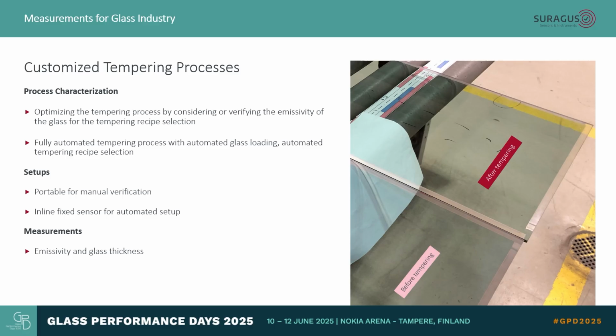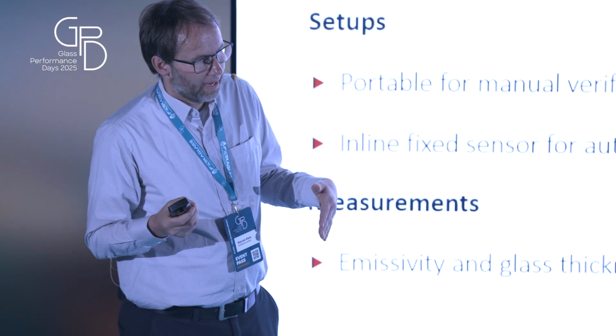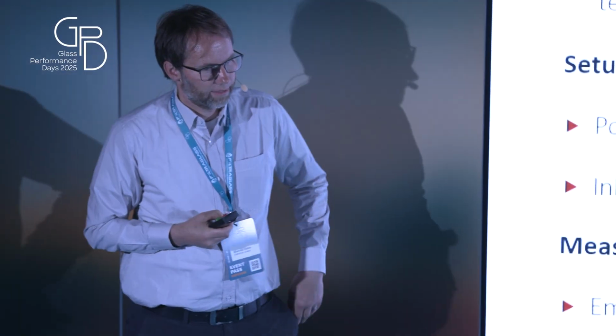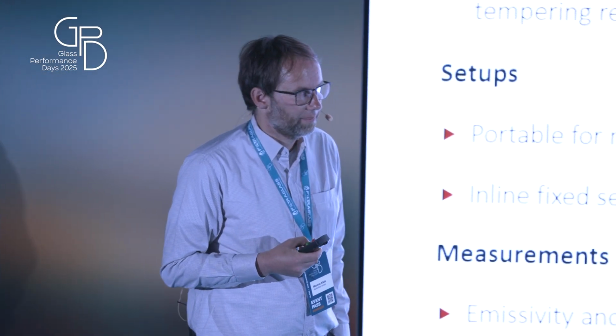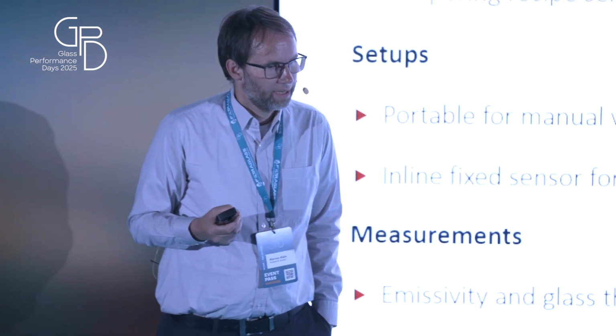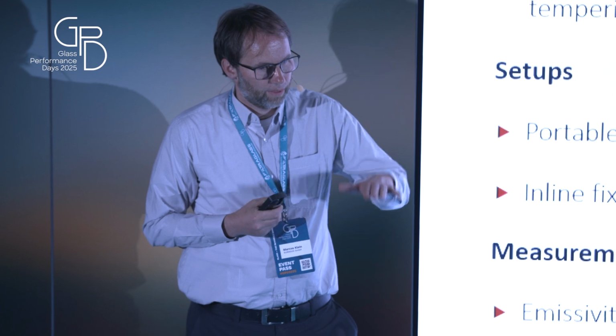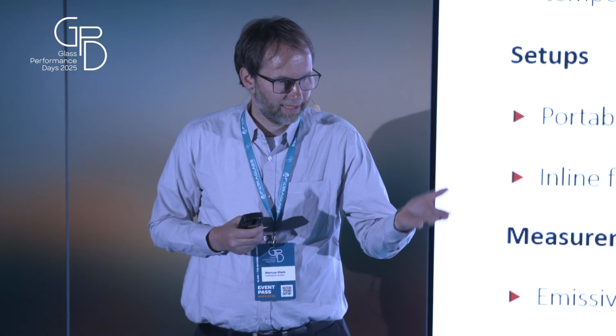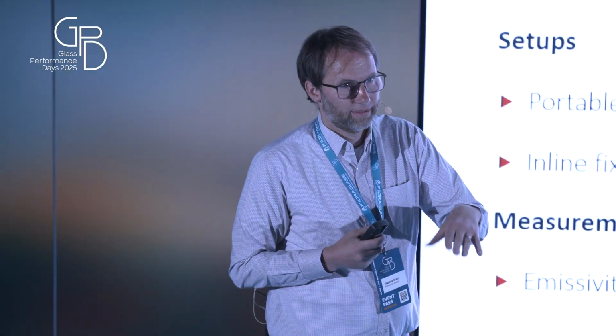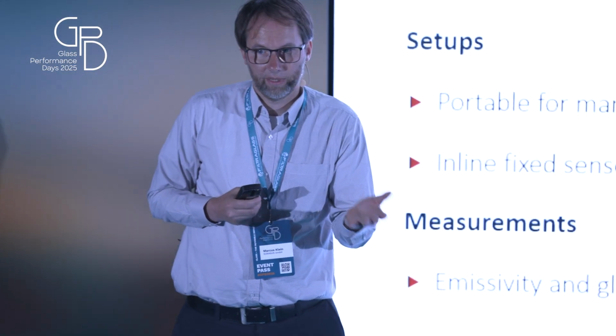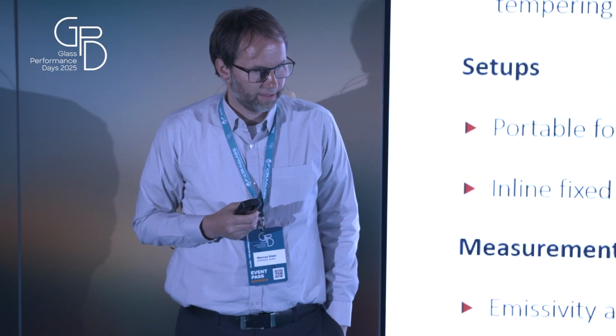In the tempering, it's important what kind of glass you temper. Do you have a single low E? Do you have double low E? Do you have triple low E? And typically, the people running the tempering furnace need to select the right recipe. And in a night shift, there can be mistakes. So one approach is to measure what type of emissivity I have, what is the glass thickness, and also we can check whether the coating is on the right side. Tempering the coating on the wrong side is also an issue. So this can be inspected.